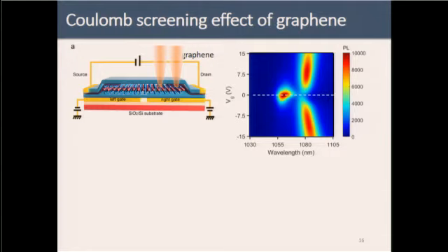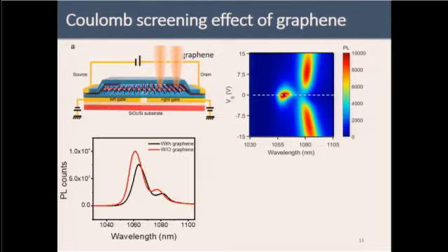where we have no charged exciton in the state. That means the carrier concentration is not playing a role here anymore. And then when we compare the area with graphene and without graphene, we find that the spectrum with graphene has a red shift, which is around 6 millielectronvolts.